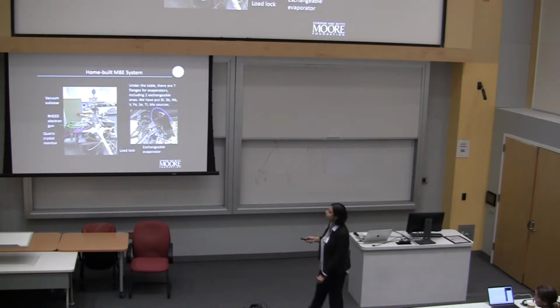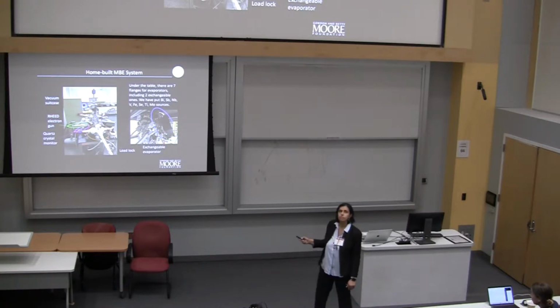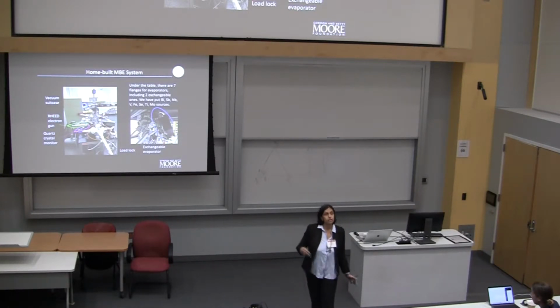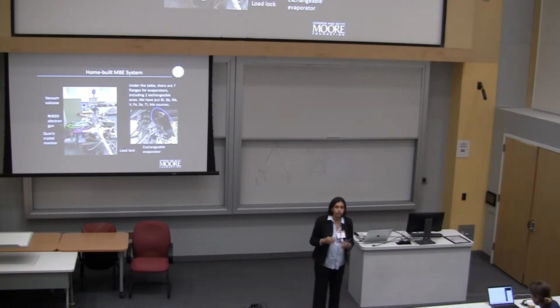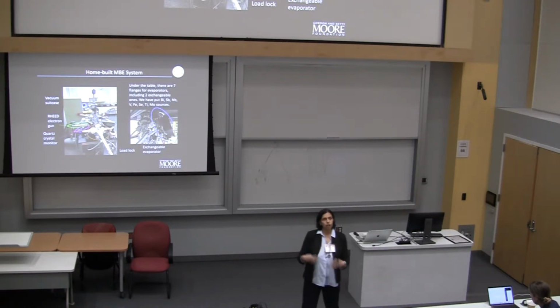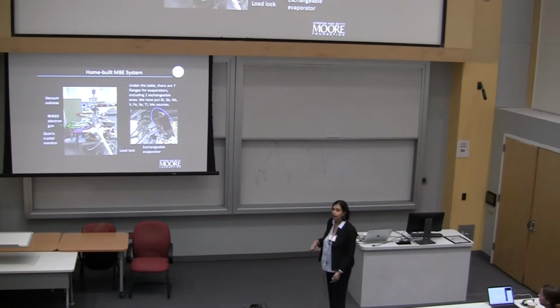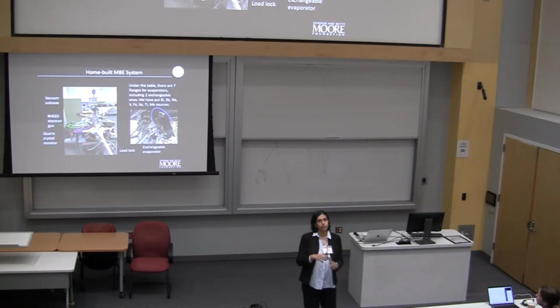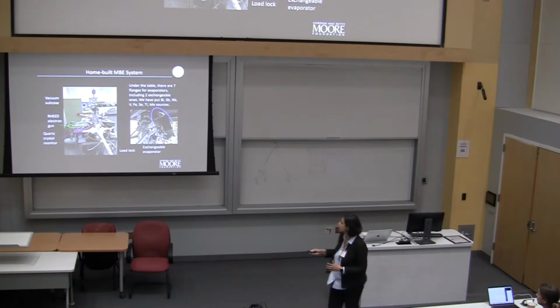So what are the main components of an MBE system? You need a vacuum chamber, which you can't see very well here. I'm sorry about that. You need a RHEED system. This is a RHEED I'll show you in a few minutes. RHEED is really critical because it allows you to see the film as it's growing. You need a quartz crystal monitor to know how much material you're evaporating, as a rate of evaporation per second or per minute. In our case, we have something called a vacuum suitcase. So we take our MBE-grown films directly from our MBE systems to the STM without breaking vacuum using this vacuum suitcase.